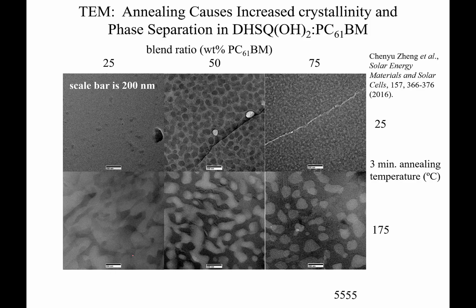So what we're going to look at here is actually what happens during this annealing process. The annealing causes increased crystallinity and phase separation, in particular with this material, DHSQOH2. That's a hexyl side group. This hexyl side group squaraine does not mix well with PCBM. So if we have a 50-50 mixture in here, what we can see with these transmission electron microscope data is